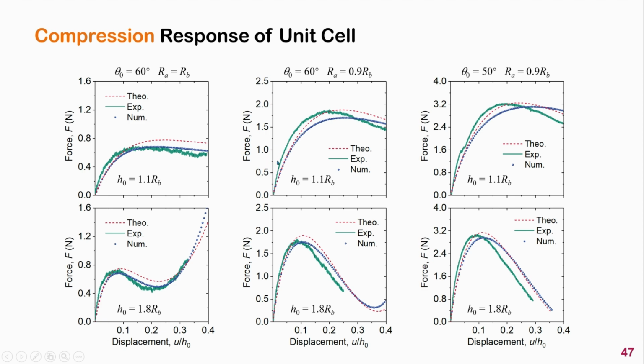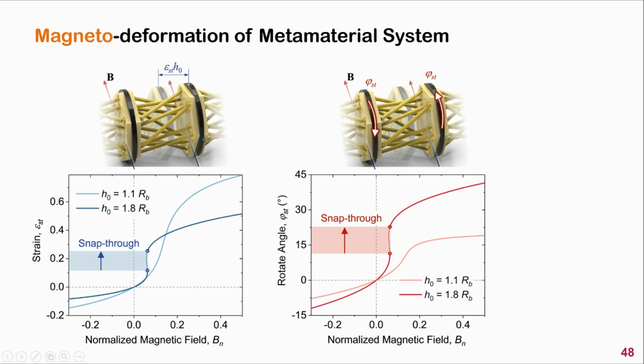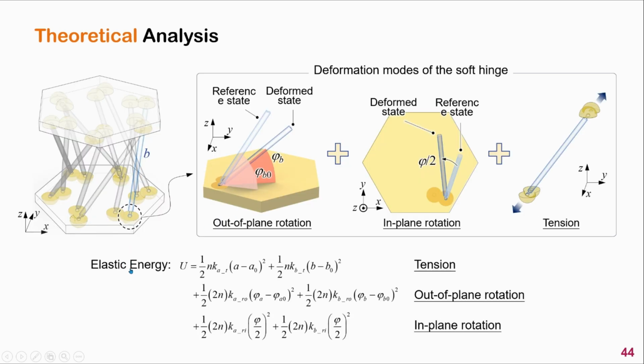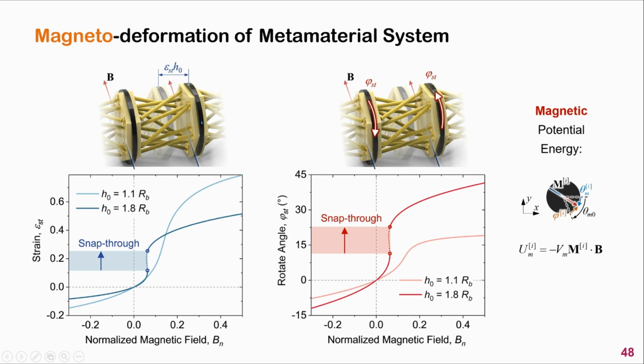Now, building on the analytical model, we investigate the deformation of the metamaterial system under an external magnetic field. In this case, we need to account for the magnetic potential energy in addition to the previously mentioned mechanical potential energy shown here. Using the total potential energy, we can obtain the deformation of the metamaterial system for a given magnetic field. Here the left panel is for the translational movement, and the right panel is for the rotational movement. H0 denotes the initial height of the unit cell structure. We can see that for a metamaterial system with relatively large height, a snap-through phenomenon can be observed when we gradually increase the intensity of the magnetic field.